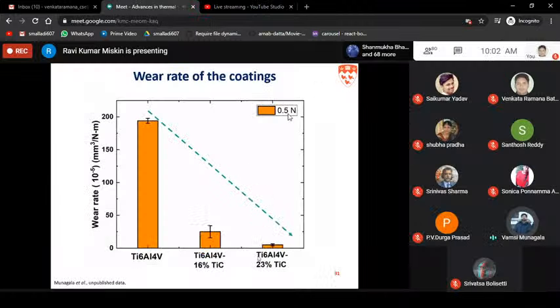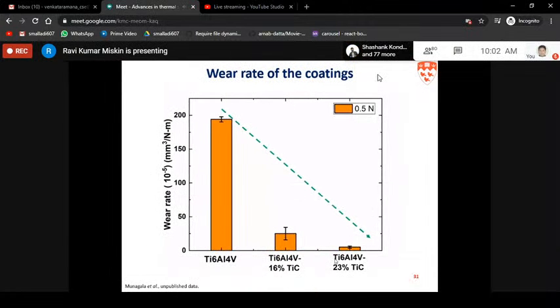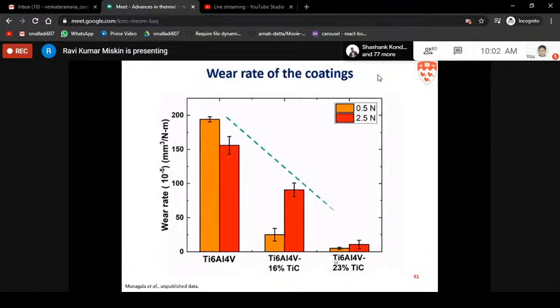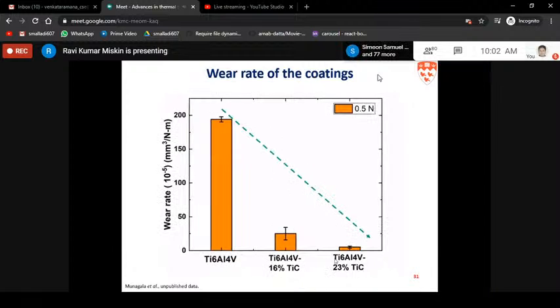The next slide. So once the friction was measured during the test, the next part was wear. Here you can see at both loads, at half Newton load, you see a decrease in wear rate also. Titanium 64, the wear rate is around 196 × 10^-5 cubic millimeters per Newton meter. Whereas when you compare our composites, that is 16% and 23%, they are at least 8 times less wearing. And in fact, with our 23% titanium carbide coating, the wear has come down by 10 times.